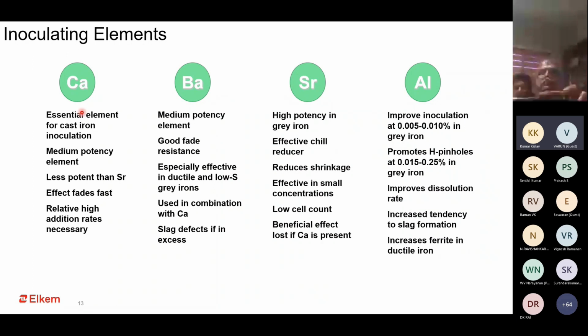Calcium is one of the most common and readily available inoculants in the casting. Sometimes we also get confused by considering ferrosilicon as the inoculant. Ferrosilicon is not an inoculant. It behaves as an inoculant only because it has some calcium in it. Any ferrosilicon which we buy from the market would have about 0.1 to 0.4, 0.5% of calcium in it. And this calcium is what makes sure that our ferrosilicon also acts as an inoculant. It is an essential element. Most of the inoculants have calcium inherently in them, except maybe 1 or 2.